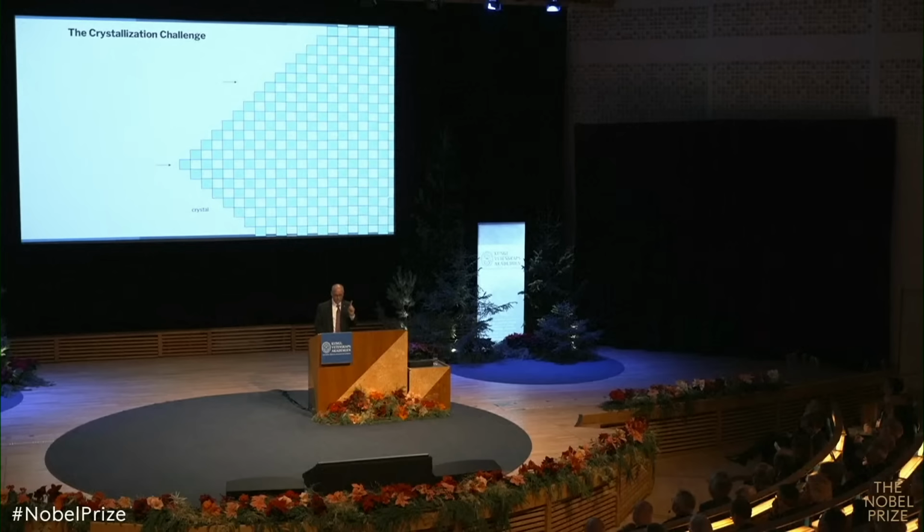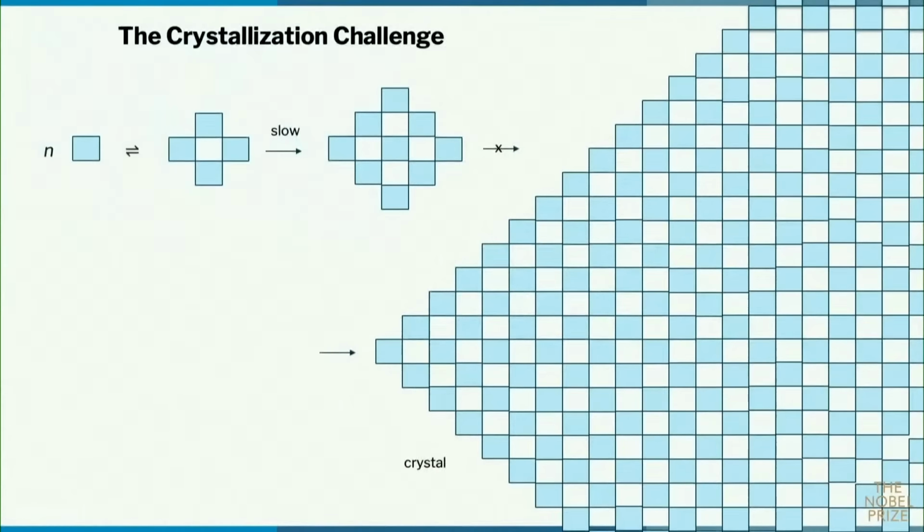So that's one thing you needed to ensure, that things can be bonded and broken on the microscopic level until they are fixed in position so that they are ordered. The second important thing is that this process of coming together and separating needed to be at the right speed. If it's too slow, then you don't make large enough crystals. Okay, you make fragments.